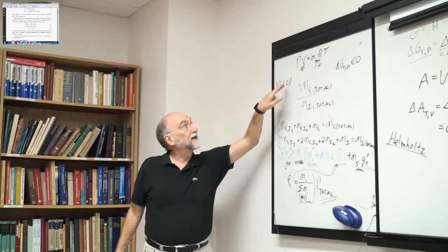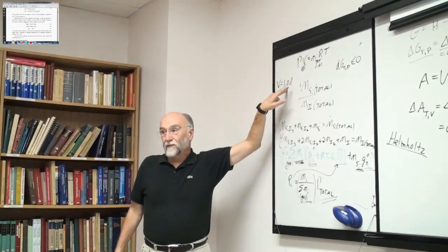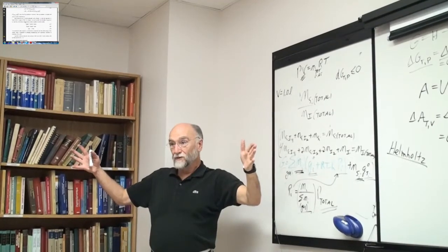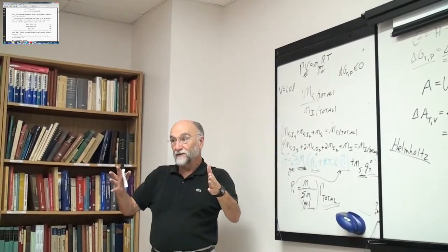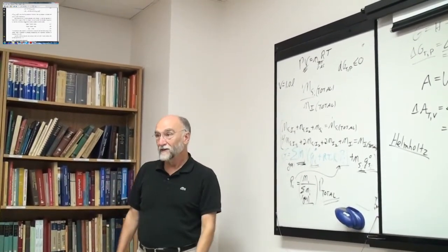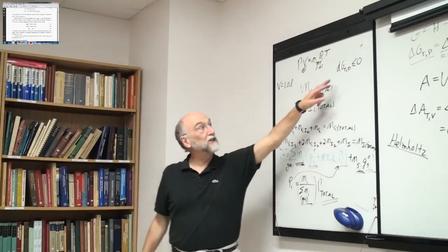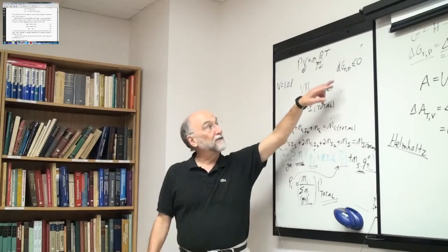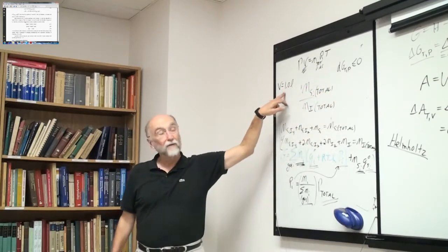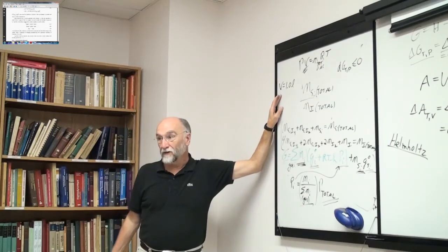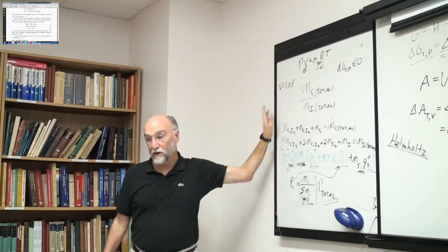Now I go back and I calculate the volume. If the volume's too big, obviously my pressure was too low, so I decrease the pressure by an increment and redo the calculation at a new pressure. I reach a new equilibrium, minimizing dG each time, until after I reach equilibrium, the volume that I calculate is the one I want. That's easier than trying to reformulate the equations every time. So that's how it works under different constraints.